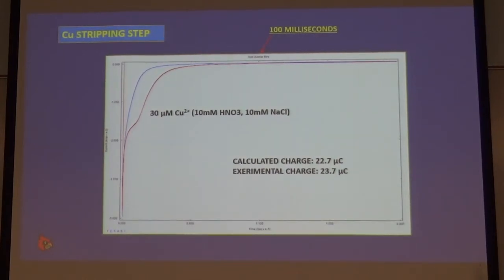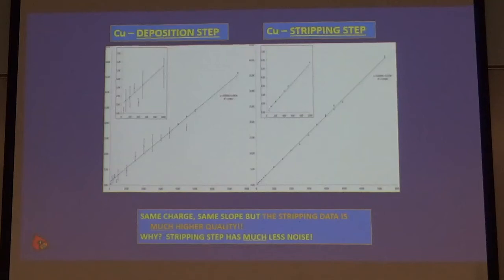Well, turns out that's a good thing. If we prepare a calibration curve where we're plotting, for different copper concentrations, the charge we get, this is the calibration curve you get if you use the deposition charge. It's nice and linear. If you do the same thing but use the stripping charge, which is occurring much faster, you get a linear calibration curve. They both have the same slope. They should, because the charge that you're getting from oxidation and reduction should be identical. So they should have the same slope, and it does.